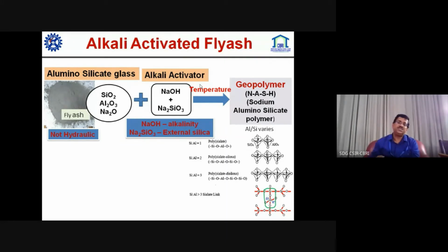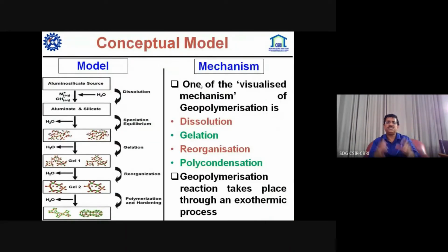So we are adding GGBFS up to 20 to 25%, which is initially converting into calcium alumino silicate polymers, and because these exothermic reactions generate energy, we don't require any heating during making the binder. So the mechanism is dissolution, gelation, reorganization, polycondensation. In dissolution, we make sodium hydroxide or sodium silicate with water in aqueous form, and it is added to our aluminosilicate source, that is fly ash, GGBS, and only water is added in making these source activators.